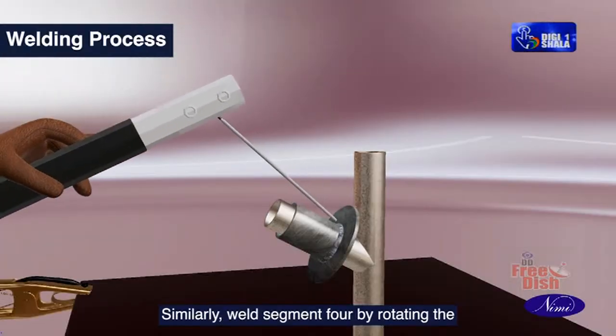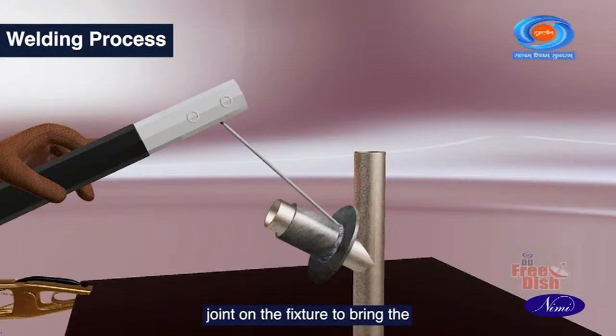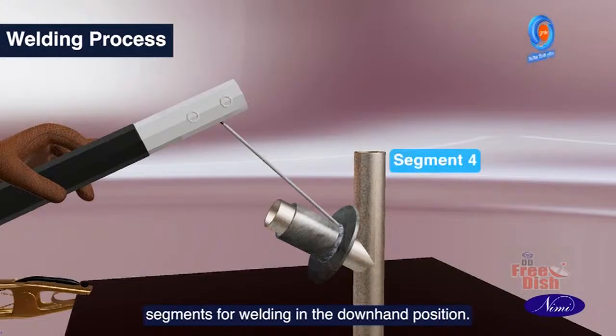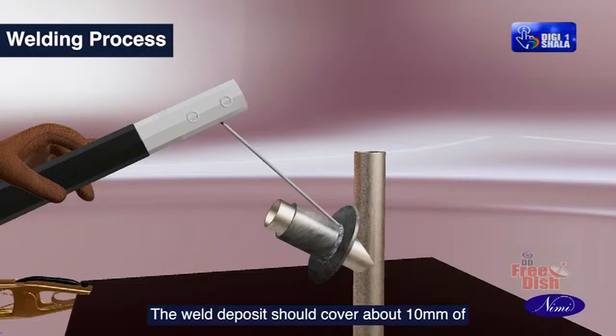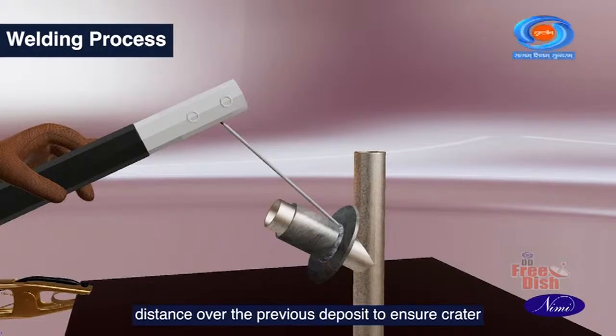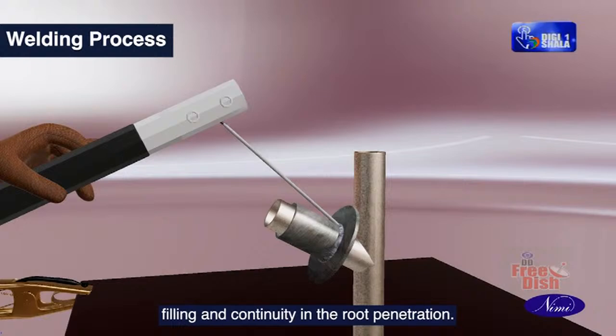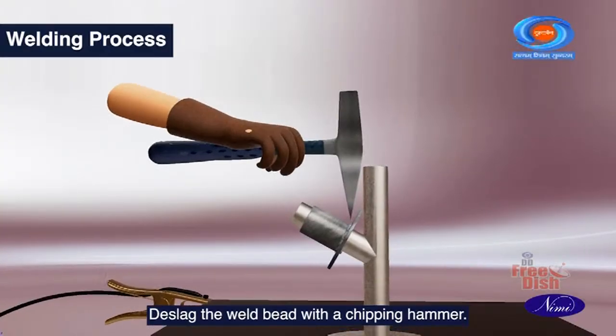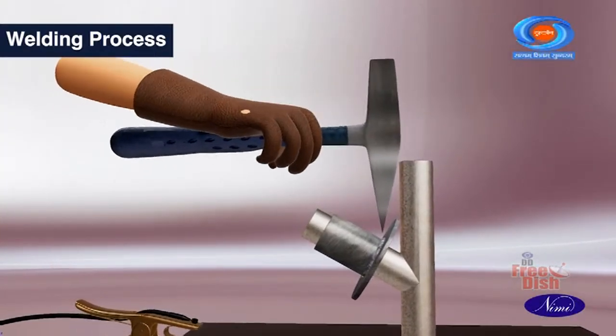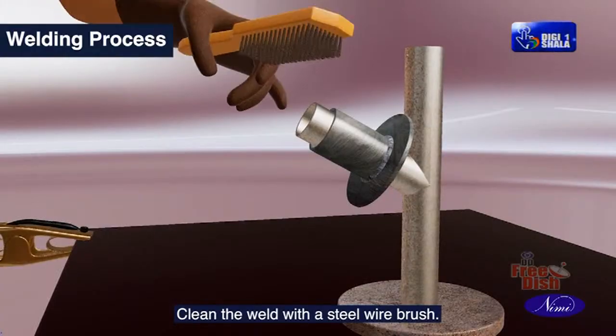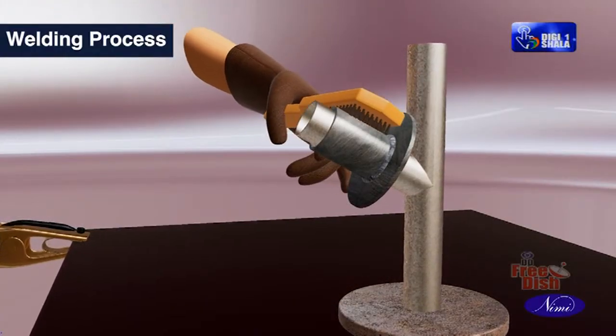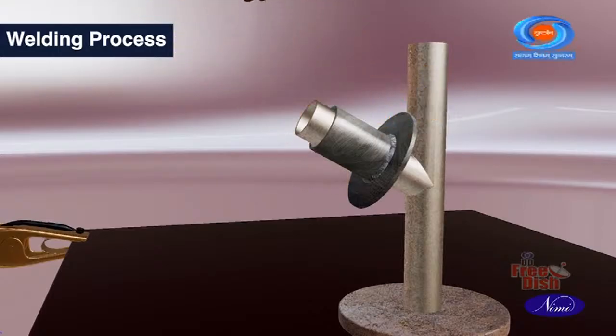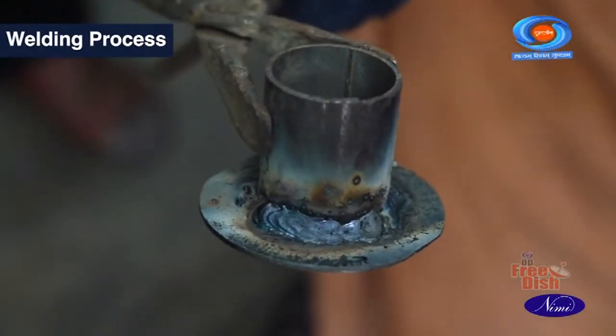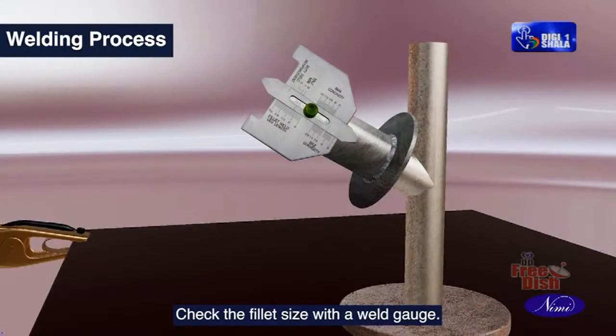Similarly, weld segment 4 by rotating the joint on the fixture to bring the segments for welding in the downhand position. The weld deposit should cover about 10 mm of distance over the previous deposit to ensure crater filling and continuity in the root penetration. Deslag the weld bead with a chipping hammer. Clean the weld with a steel wire brush. Check the fillet size with a weld gauge.